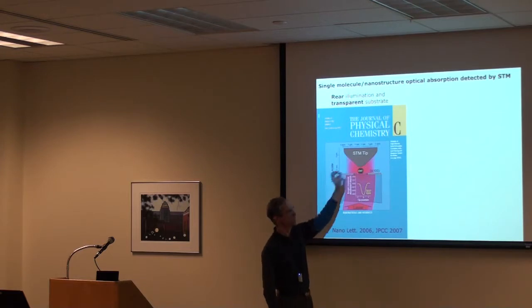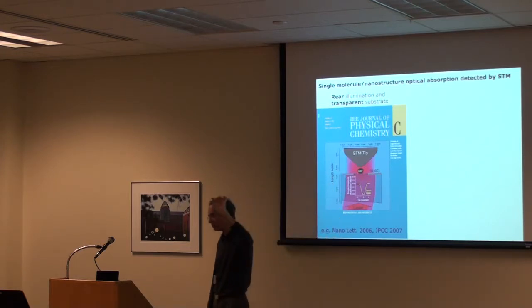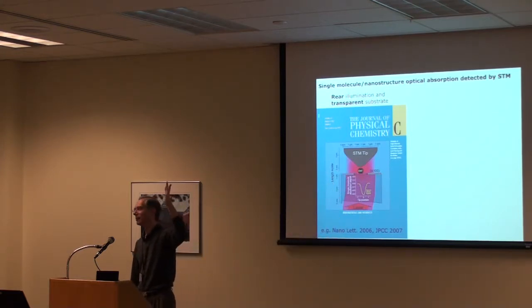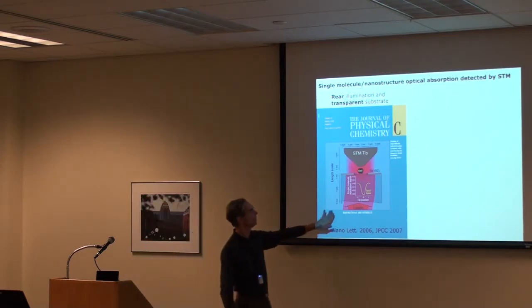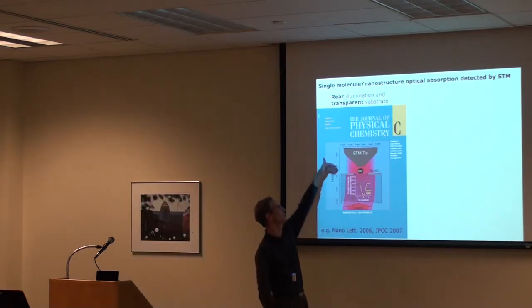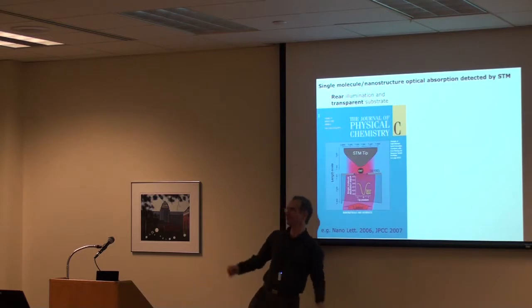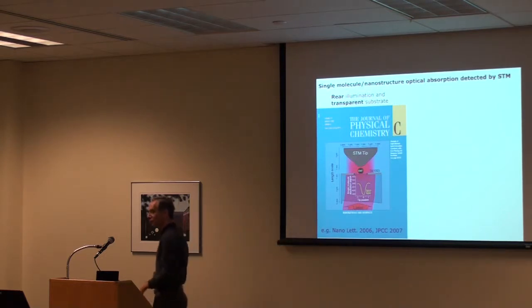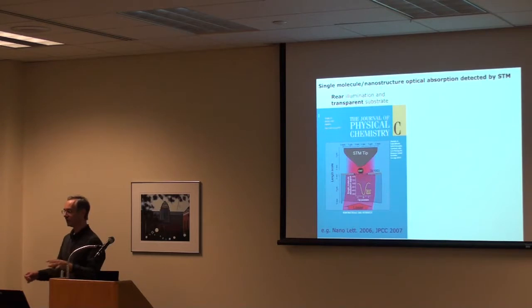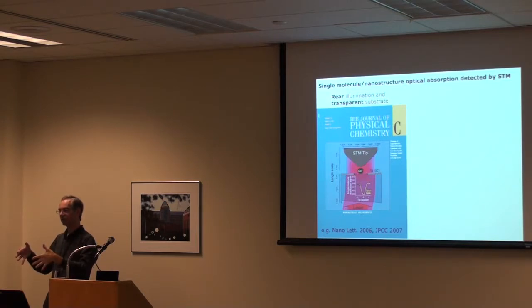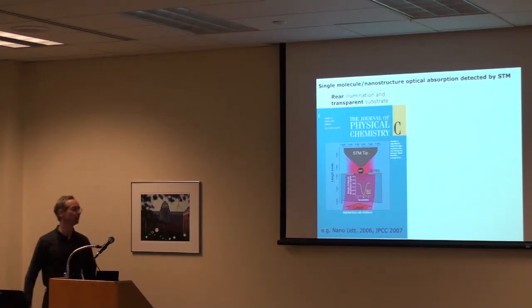So in this case, you would have to use a carbon nanotube that has an absorption maximum that lies within the band gap of the silicon in order to get your laser through. You might say, well, why don't you just shine the laser in from the front, and then you don't have to get through the substrate? You don't want to do that. The reason is, when you shine the laser from the front, the light will invariably be absorbed by the tip to a very significant degree, and you have a macroscopic object that's supposed to scan things with angstrom resolution that you're heating. That is a very bad idea. It just makes things go all over the place.